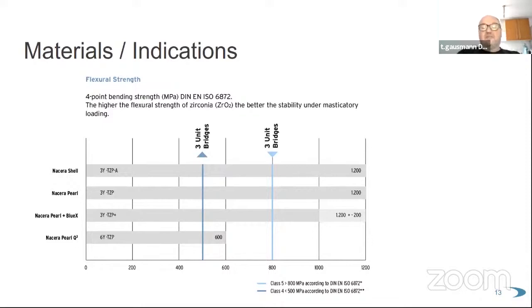But the point is, they measure an average through the complete disc. So on the bottom, where they've got less cubic material, for sure they've got more strength. And on top of the disc, in the incisor, where they've got much more cubic material in the mix, they've got less value. So when you look at people like Amann, they state that they've got 1100 megapascal in Generation X on average. When you go to the details, you can see that they've got 850 megapascal in the incisor.